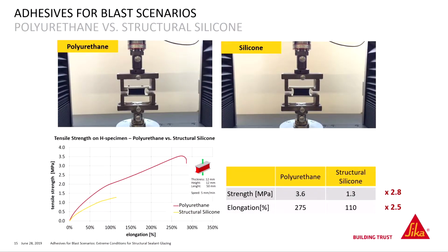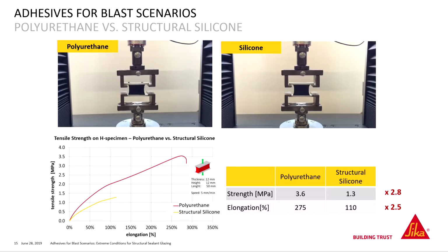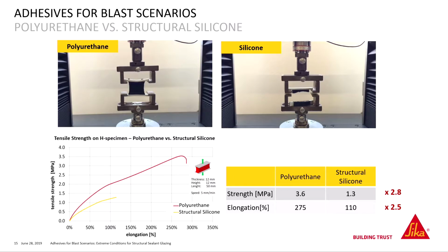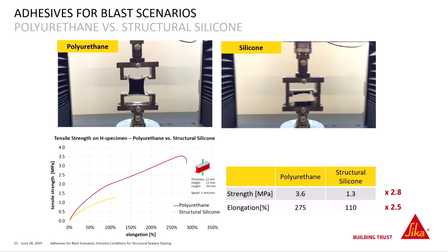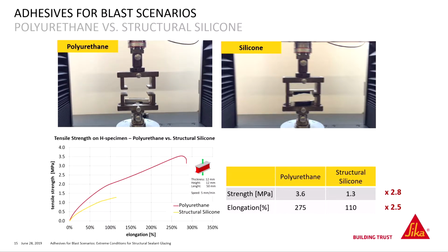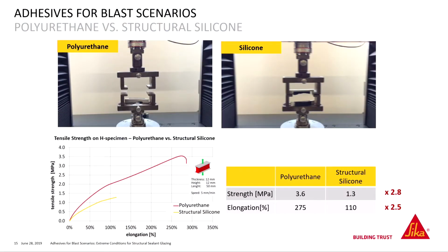Therefore, we have compared some results for structural silicone and polyurethane. I would like to show you, as a start, the behavior of silicone and polyurethane. So I think that's quite impressive. When we look at the values, we have almost 3 times higher tensile strength and 2.5 times higher elongation at break. So that paves the ground, that sets the environment for further tests.